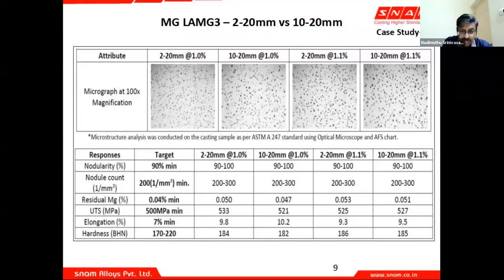And we had the 1-inch Y block as the test bar. We did step blocks, and then we had the AFS coupons for the microstructure analysis. Now, based on this, you can find the nodularity is almost the same. The nodule count is similar. The residual magnesium, interestingly, is also similar. We meet the ultimate tensile strength for the 500/7 grade, for which we had the chemical composition. We met the elongation, and we met the hardness. So the 2 to 20 mm distribution performed as well as the 10 to 20.